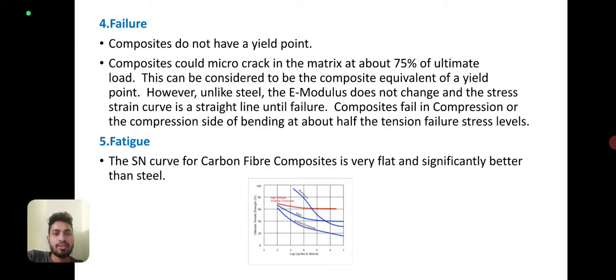Failure. Composites do not have a yield point. Composites could micro crack in the matrix at about 75% of ultimate load. This can be considered to be the composite equivalent of a yield point. However, unlike steel, the E modulus does not change and the stress strain curve is a straight line until failure. Composites fail in compression, or the compression side of bending, at about half the tension failure stress level. Fatigue. The SN curve for carbon fiber composites is very flat and significantly better than steel.